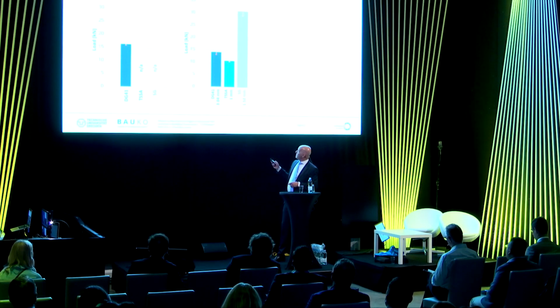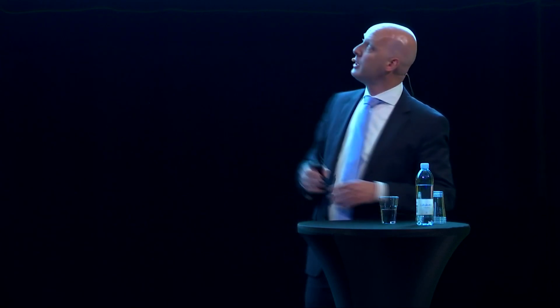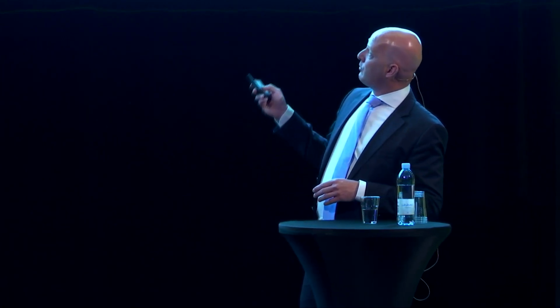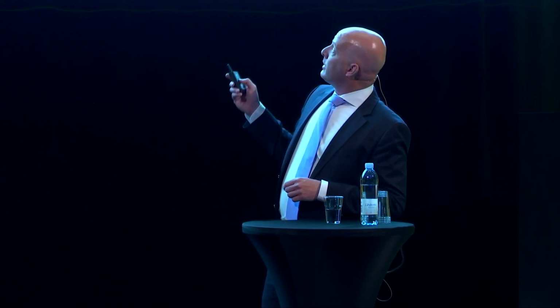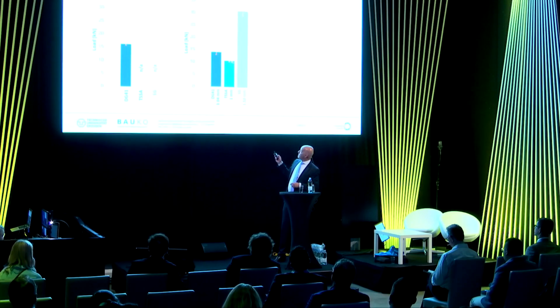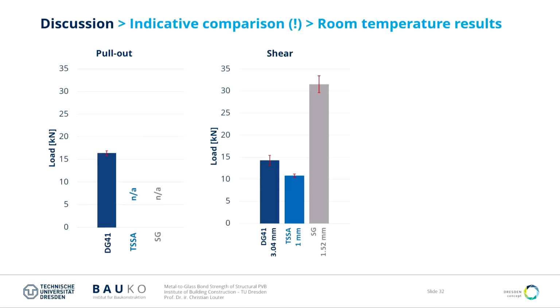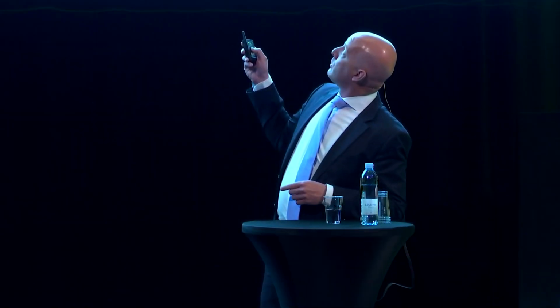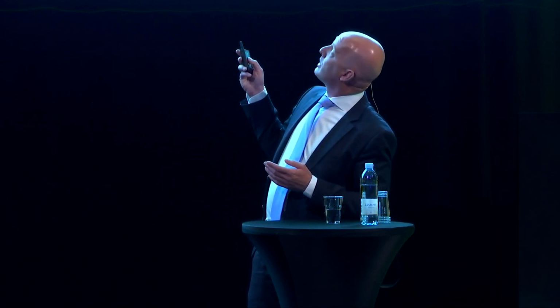If you compare that, for instance, with TSSA, we did the same kind of test with TSSA, but at a different machine, different conditions. So you have to be careful with interpreting this, and also different thicknesses of interlayer, of course. So just want to mention that. Then you can see that it's a little bit higher than that. Also, TSSA shows whitening, as you might know, at a certain load, which is about 50% of this load. The same test for SentryGlas, again with a different thickness, so you cannot perhaps directly compare it, just to give an indication. And you can also see that SentryGlas also shows this relatively high, acceptable scatter in the results there.